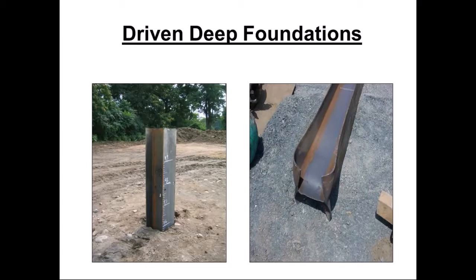So once that correlation is developed, the blows per inch for capacity, then the inspector is going to verify all the other piles that are installed are driven to that same criteria using the same driving system that was used for the test piles. And then the photo on the right, that's typically what you would see of pile damage if a pile was driven to bedrock, or if you had cobbles or boulders.